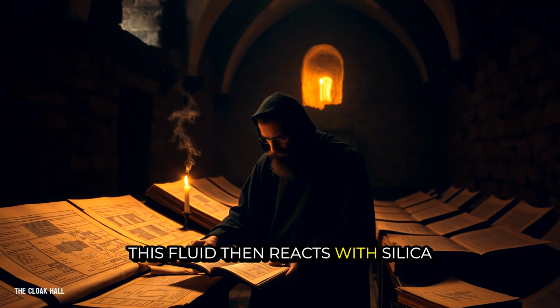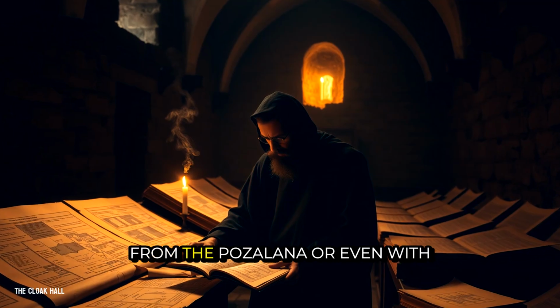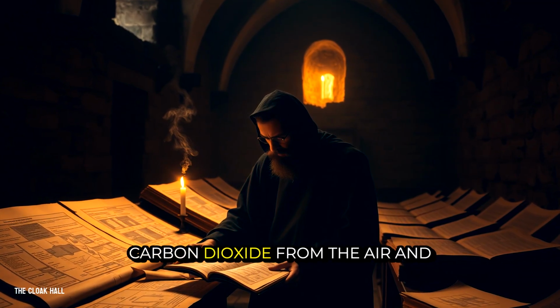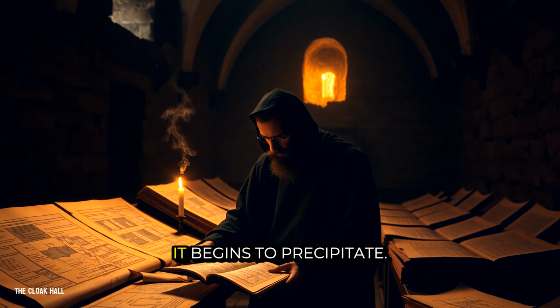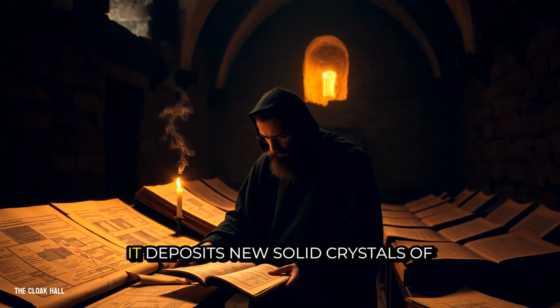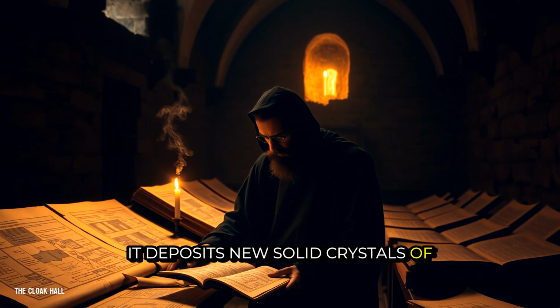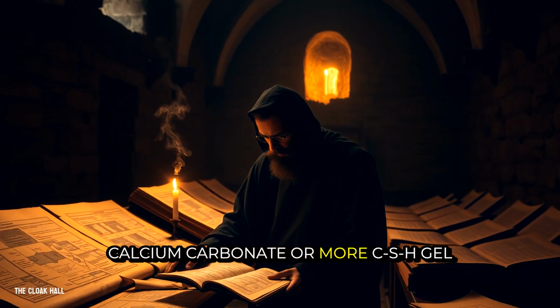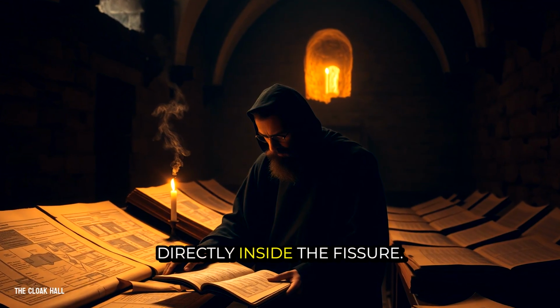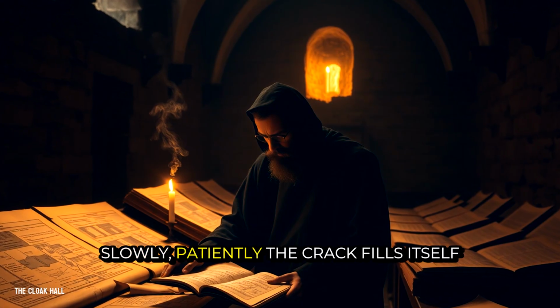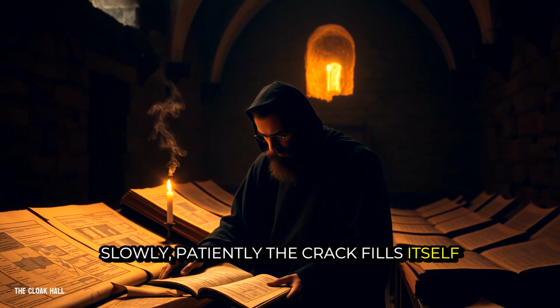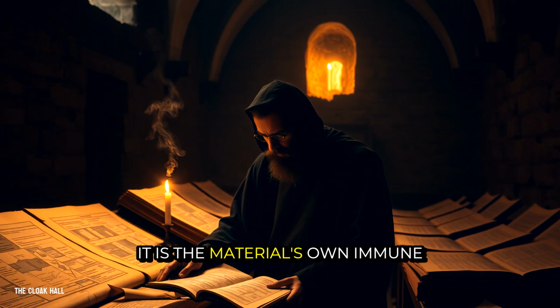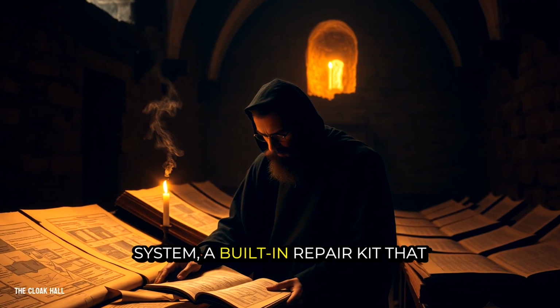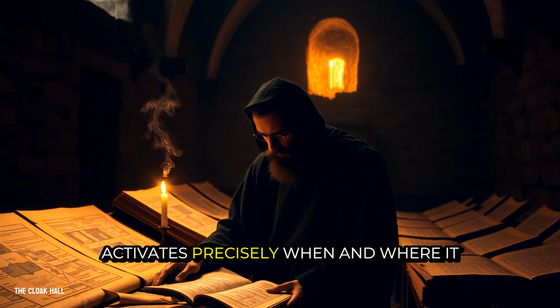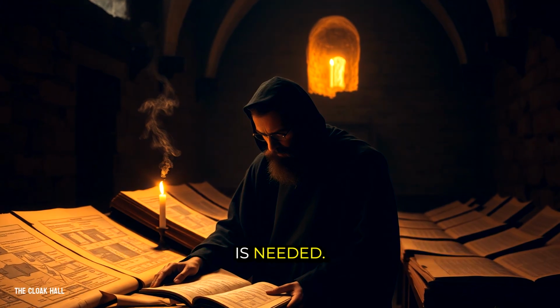This fluid then reacts with silica from the pozzolana, or even with carbon dioxide from the air, and it begins to precipitate. It deposits new, solid crystals of calcium carbonate or more CSH gel directly inside the fissure. Slowly, patiently, the crack fills itself in. It is the material's own immune system, a built-in repair kit that activates precisely when and where it is needed.